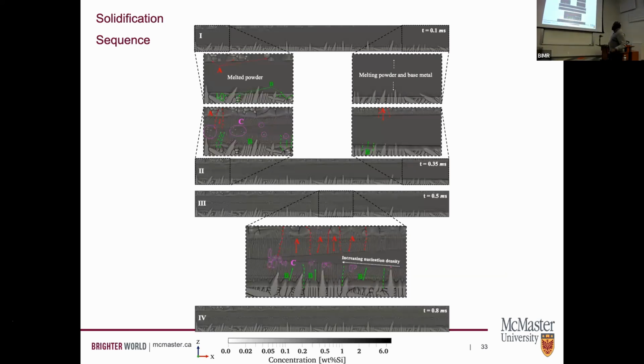What we find is, depending on which direction we're in, we're getting first an epitaxial growth from the substrate, and then we're getting nucleation ahead of these fronts. In solidification, we call this the columnar to equiax transition, where you start off with these lenticular solids that grow, and then ahead of that solid, you get these localized nuclei of equiax grains.